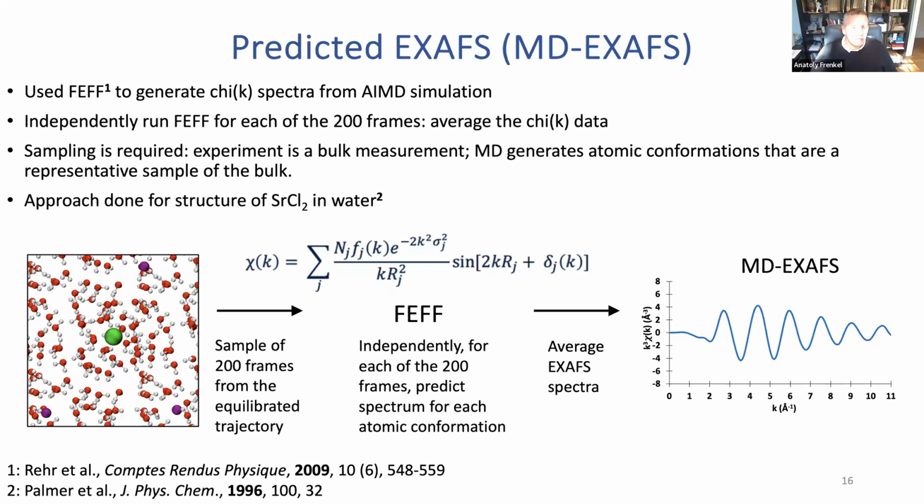So what's the meaning of this equation? The meaning, I mean, that is just the chi-k, the EXAFS equation. But that equation is obtained in the approximation that your unknown g(r) is Gaussian or nearly Gaussian, which is not the case here. So how can this equation be useful? Yeah, maybe that's not a good idea to put that equation there.